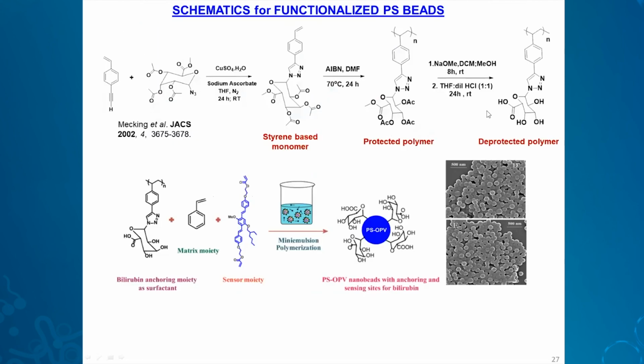So this is the synthesis shown here, how the styrene monomer was made with this glucuronic acid protected polymer. Then it was polymerized, and after polymerization, it is deprotected. So now the polymer became water soluble. Normally, polystyrene is hydrophobic, but now with this appendage, it became amphiphilic. So what we have done is that we use this polymer as a surfactant to bring about miniemulsion polymerization of styrene, in presence of this fluorescent cross-linker.